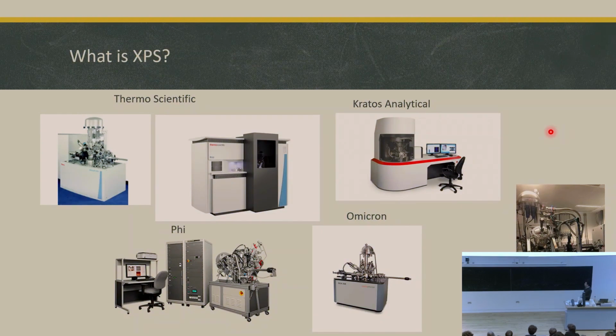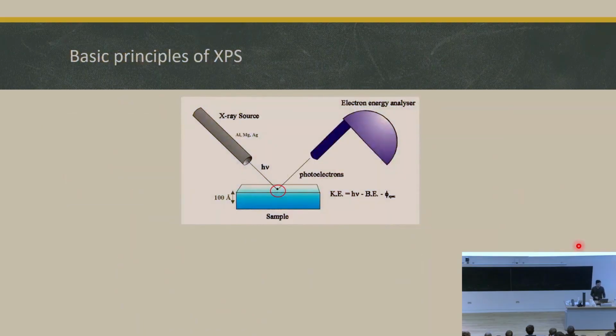So what is XPS like? There are many manufacturers shown here. And we have this one, and this one, 3 XPS instruments in Cambridge. They may look different, but the basic principles are the same. So when an X-ray source, usually coming out from aluminum, magnesium, or silver, shines on the sample, the electrons will absorb the energy and be kicked out as photoelectrons, which are collected by this electron energy analyzer. So the X-ray may penetrate dozens of microns through the surface, but only the top 10 nanometers, where the photoelectrons come from, have the characteristic information, which gives us the elemental information.